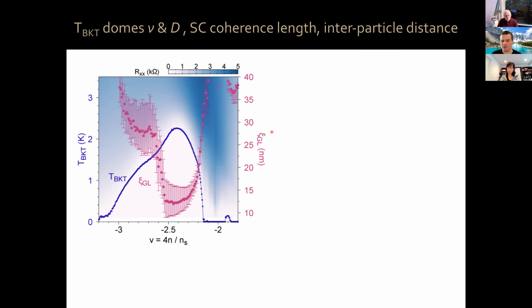Now, this is an extremely short superconducting coherence length, because you have to remember that these Moiré superconductors are the lowest charge density superconductors that exist by far, by more than an order of magnitude. In fact, let me plot here the average interparticle distance as a function of filling factor, and it's like this. So you can see that near optimal doping, your superconducting coherence length is actually of the same order as the average interparticle distance.